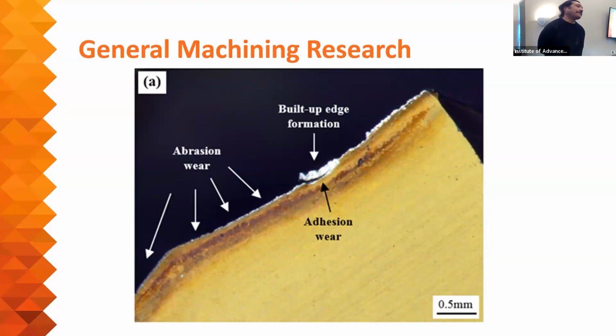Problem is that that piece of gum stuck on the surface, as soon as it tries to get removed during more cutting, that removal process sort of like picks at the cutting edge. And the main issue is it starts to deteriorate the cutting edge, and it leads to tool wear, which we call adhesion tool wear. Unfortunately, when you do machine duplex stainless steel, it's a very sticky material, so it has a high tendency for this to occur. Still unknown how or why it happens.